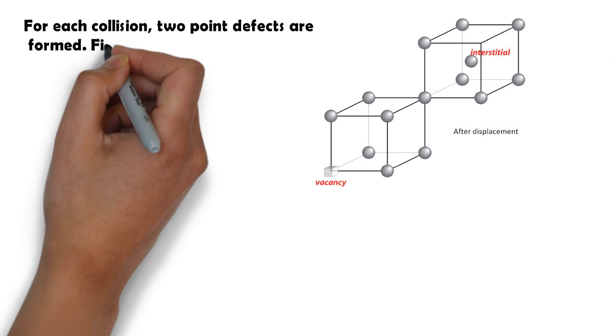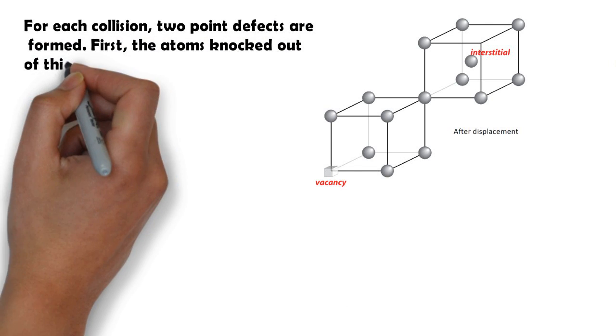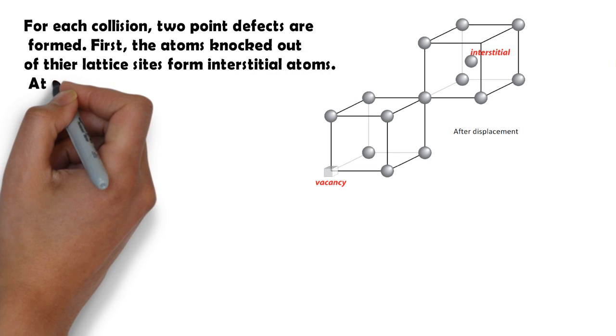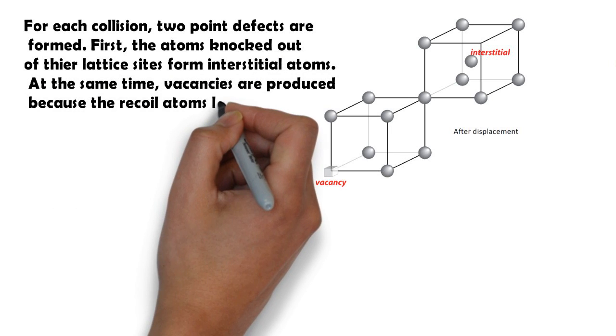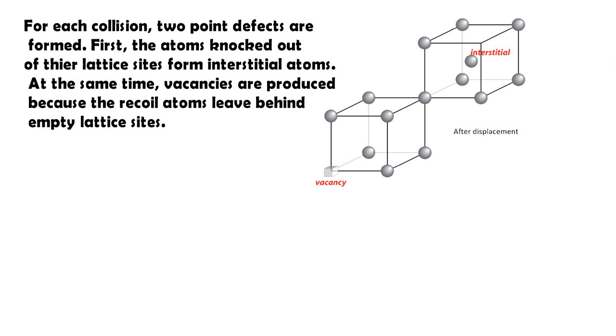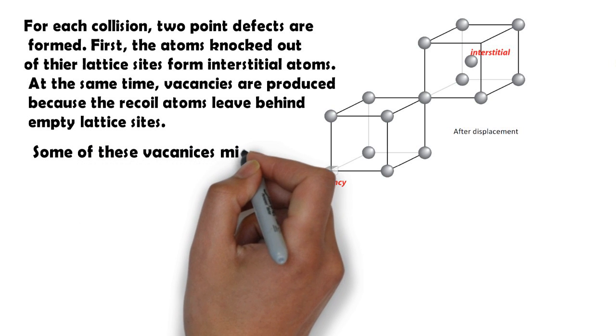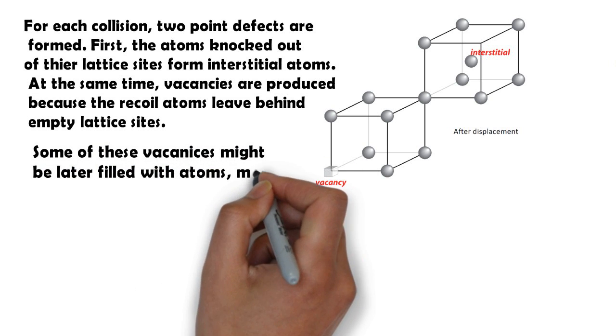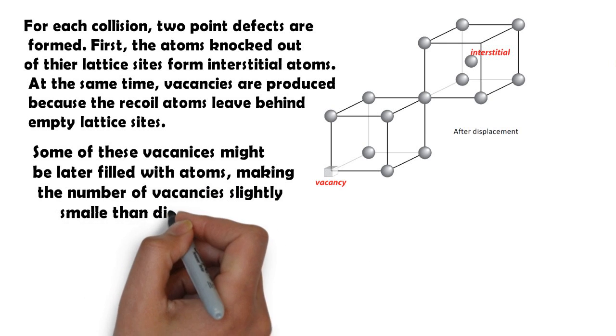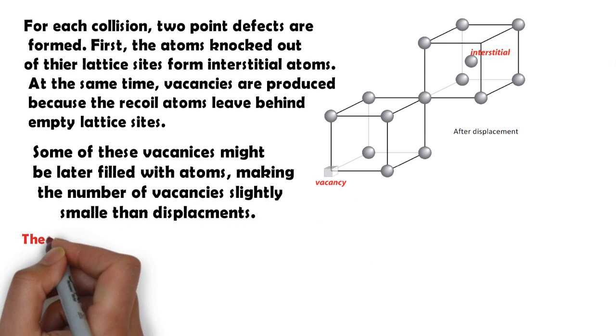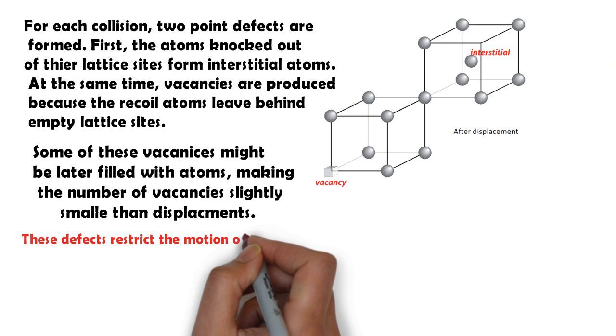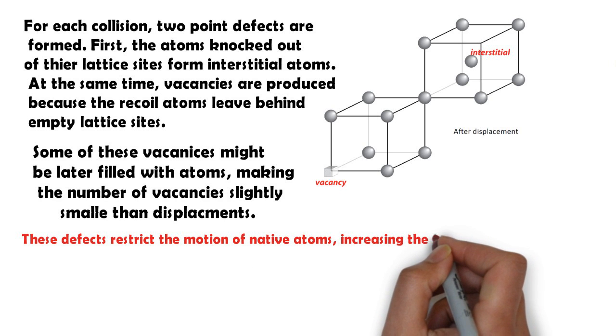First, the atoms knocked out of their lattice sites form interstitial atoms. At the same time, vacancies are produced because the recoil atoms leave behind empty lattice sites. Some of these vacancies might be later filled with atoms, making the number of vacancies slightly smaller than displacements. These defects restrict the motion of native atoms, increasing the hardness of the material.